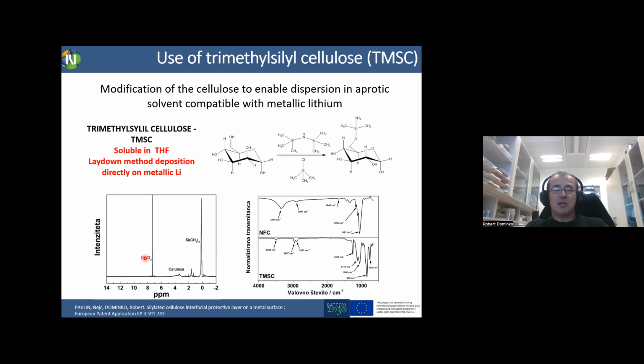And of course, cellulose is hydrophilic, so you cannot dissolve it in solvents which are compatible with the metallic lithium. For that reason, we decided to modify cellulose, and we form trimethylsilyl cellulose, so-called TMSC. And this one is soluble in THF, which we know is compatible with the metallic lithium. And by careful modification, we can exchange the 3 OH groups that are here with trimethylsilyl groups,